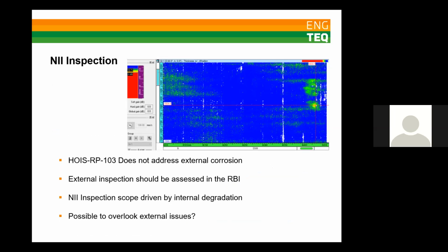So non-intrusive inspection is really for the detection of internal corrosion only. External corrosion isn't addressed. But this is obviously the case for an intrusive inspection as well, of course. So the requirements for an external inspection should be set in the RBI. This includes the inspection frequency, which might be different to the internal interval. But one thing that needs to be considered is, is it possible to overlook external issues? So quite often we inspect vessels with more external corrosion than internal corrosion.